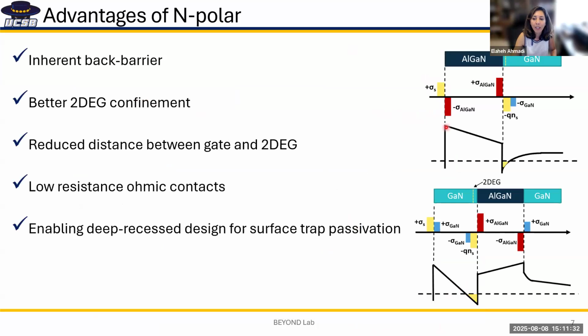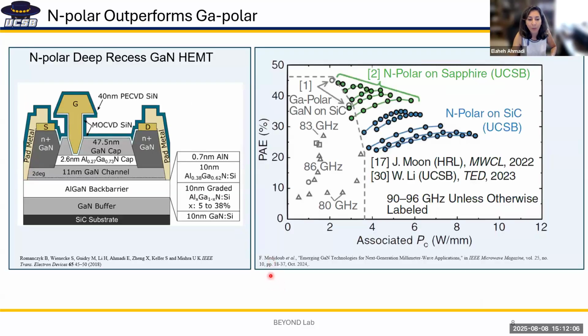Now, nitrogen polar, because of this inherent back barrier, has some unique advantages. It gives better 2DEG confinement, reduced distance between gate and 2DEG, and we can achieve low resistance ohmic contacts to nitrogen polar GaN HEMTs. It also enables deep recess design for surface trap passivation, which I'll discuss more later. Professor Mishra from UCSB, a few months ago, gave a nice talk on UCSB's work on nitrogen polar GaN HEMTs and the state of the art results that they have.